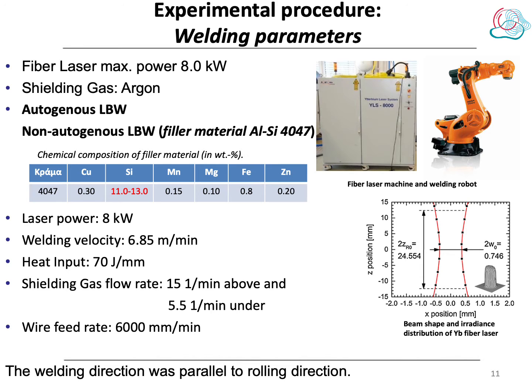For the welding, we used a fiber laser with maximum 8 kW power. Argon was used as a shielding gas for both autogenous and non-autogenous welds. For non-autogenous welds, aluminum silicon 4047 was used as a filler material. Here we can see also the welding parameters that were used.